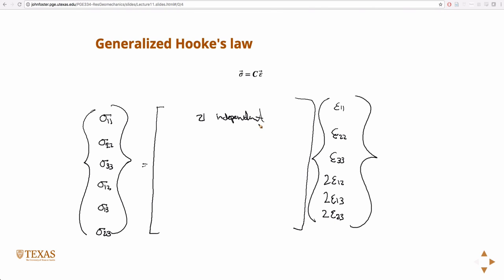And if you have infinite planes of symmetry, so it doesn't matter which direction you orient the sample. And for the most part, steels are pretty good examples of, I mean, they're not—steels technically are also a little bit anisotropic. They depend, if you test the sample, it depends on how the material was made, how it was rolled. But that dependence is usually pretty small, so that isotropy is a good assumption.